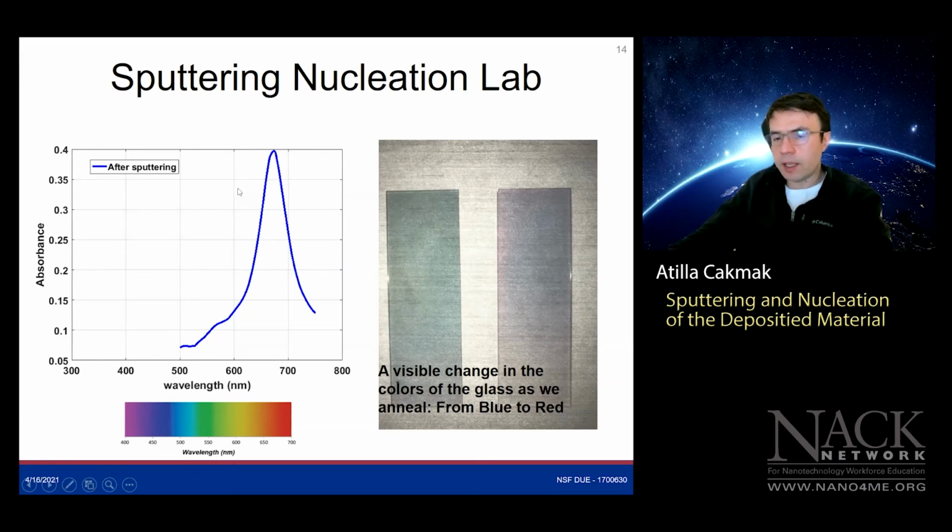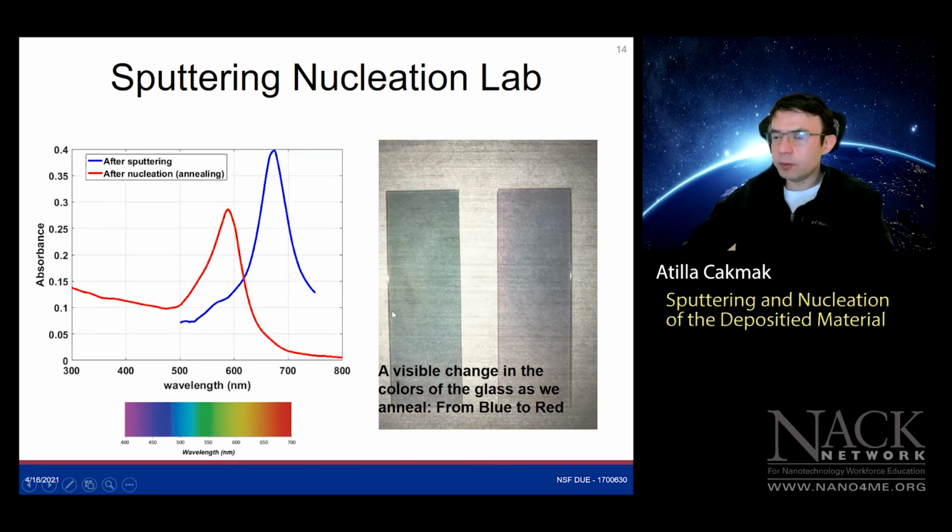So they absorb the red, they don't absorb the green, that's this part, they don't absorb the blue. So that's why they reflect back the colors that are not too much touched, and those are adding up to this interesting color, the blue and the green, but mostly green also coming into play. So as for the other one here, right after the anneal, we form these dome-like structures, uniform dome structures, and we don't absorb the red colors anymore, but we absorb more of the blue, green colors this time. And we're also absorbing quite an amount of the blue colors too.